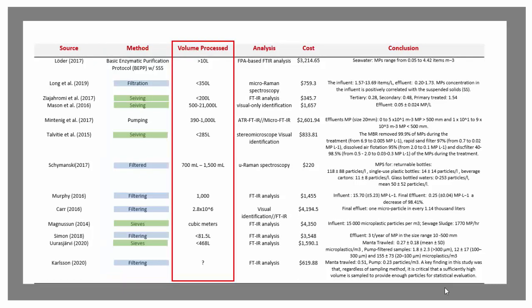There was also considerable variation in the sample size used for each of these studies. Collecting a representative sample is absolutely necessary, especially when trying to extrapolate and quantify for larger operations. For example, if you're trying to characterize the discharge from let's say a 20 million gallon a day wastewater treatment facility and the amount of polymers that are discharged to the environment, you want to capture the entire diurnal pattern throughout the day. So a 24-hour composite is probably the best route.